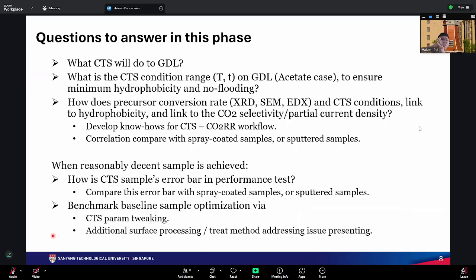Conventionally, this was addressed by buying a carbon paper coated with PTFE, so it is hydrophobic. Then you buy nanoparticles from Sigma Aldrich or wherever and spray coat them, or you prepare a magnetron sputtering target and coat it. But either you need to buy the nanoparticles from somebody, or you need a pre-made target, which is not very fast. So it very much limited the capability of combinatorial research, I would say, till now.